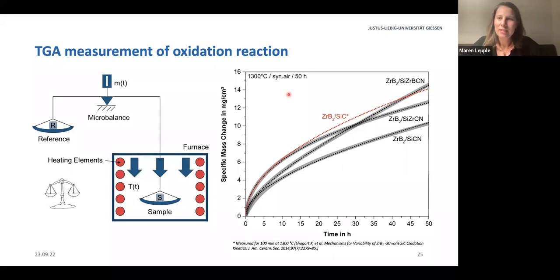Yeah, actually, it's more an environmental barrier coating than a thermal barrier coating. So the structural material, the metallic material, which we consider in this consortium is a MoCT. And yeah, molybdenum might evaporate. So actually, the polymer-derived ceramics should work as an environmental barrier coating, and usually rare earth silicates are already used, for example, for CMCs as environmental barrier coating.